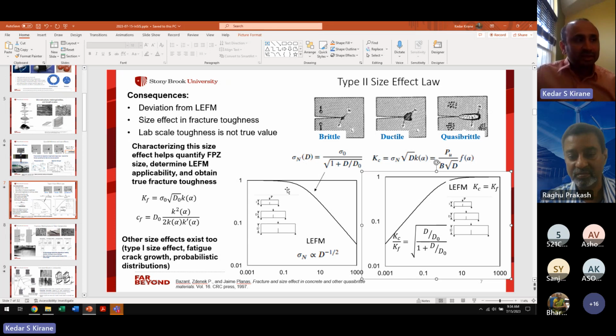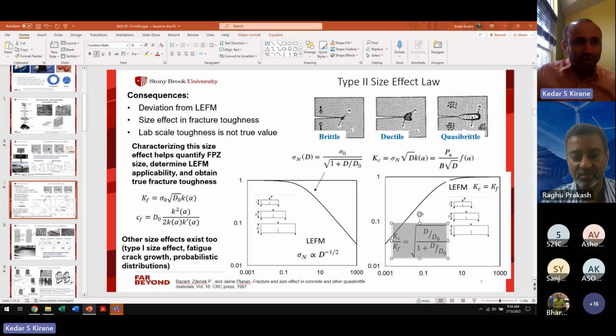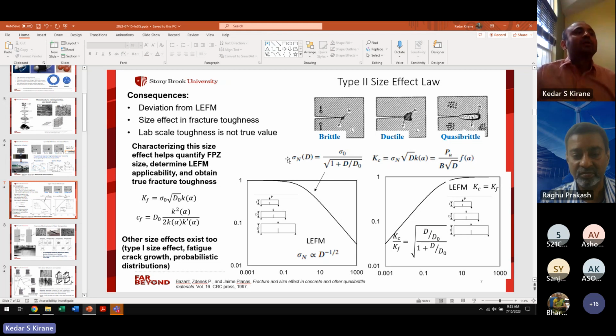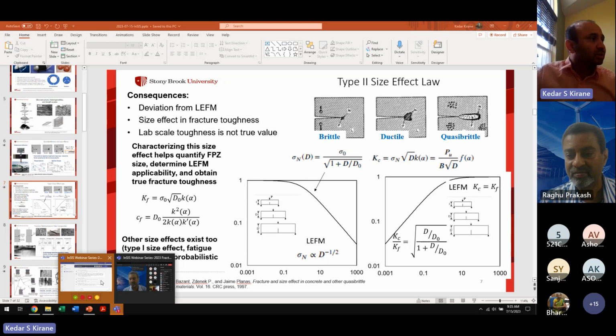So in a sense, the decrease of strength with size is related to the increase in fracture toughness with size. If we were in person on paper, I could have shown that you can derive this equation for Kc by starting from the size effect equation. It's fairly straightforward. Sigma n will be Kc divided by square root d k alpha, and if you substitute that here and solve for Kc, you will get a size dependent law. That's how the strength decrease can be directly interpreted as an increase in the fracture toughness. I don't know if I answered the question, but that's how it basically works. And note that the strength is the specimen strength, not material strength.